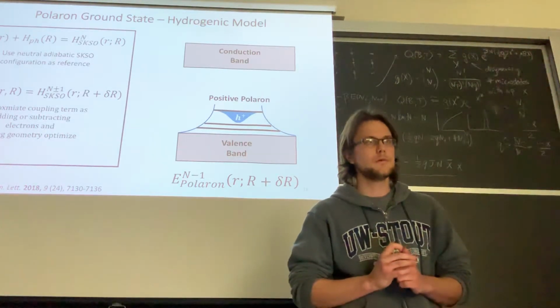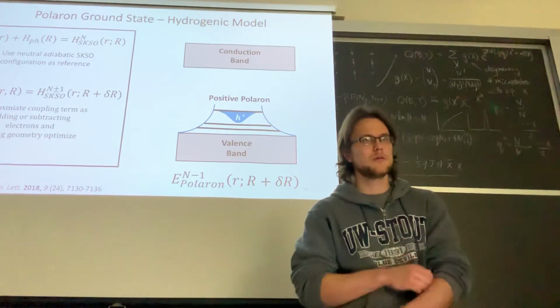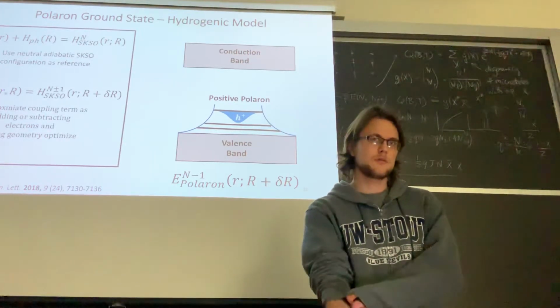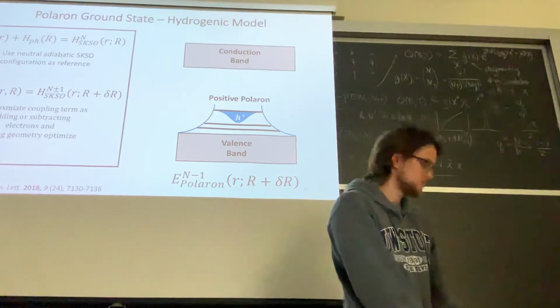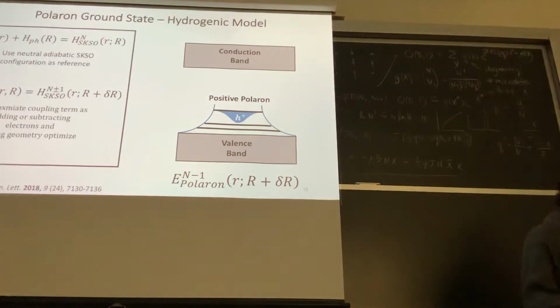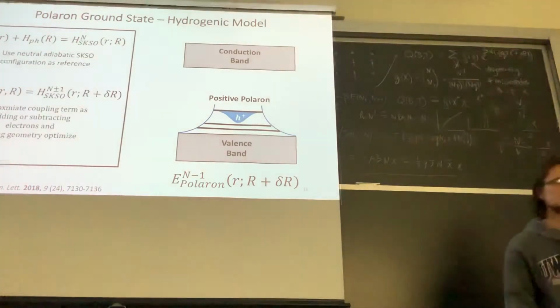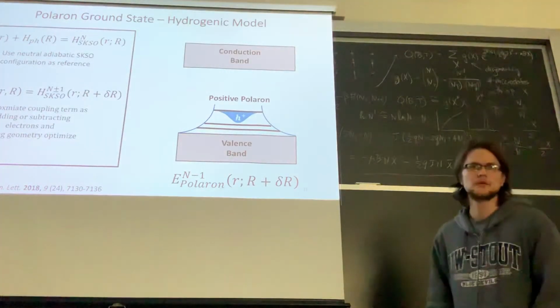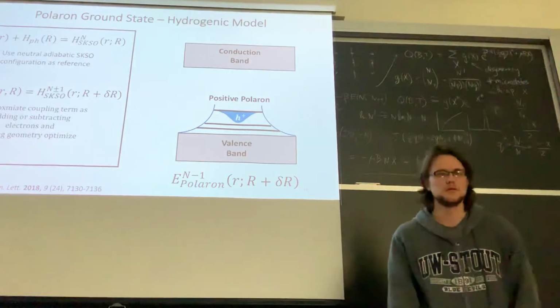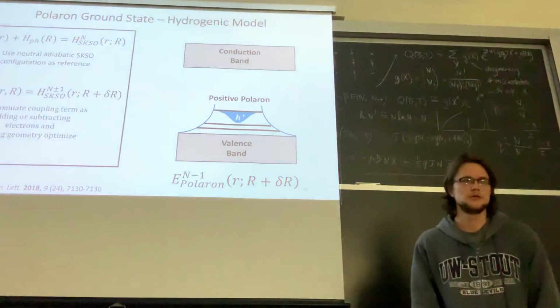You're correct, but it is like the art of the possible. If one would consider, if you permit me to comment, polaron in the periodic bulk material, then one needs to take into account non-zero momentum. It will be a traveling polaron, which adds an additional degree of freedom. So if doing periodic boundary condition calculations, one needs to recompute it at different k points, and it will be much better.